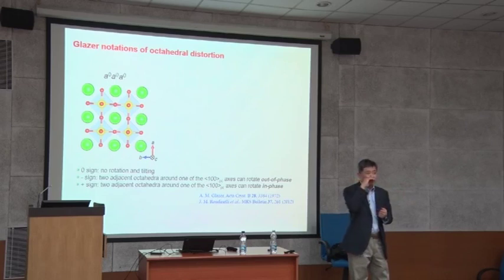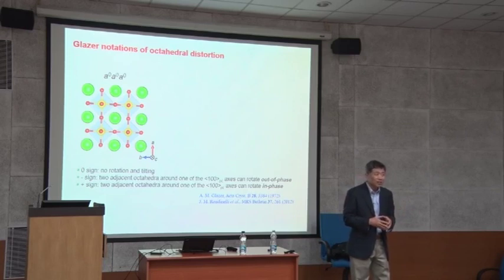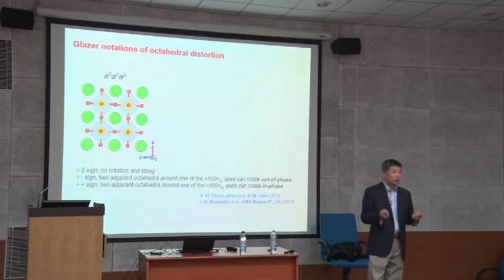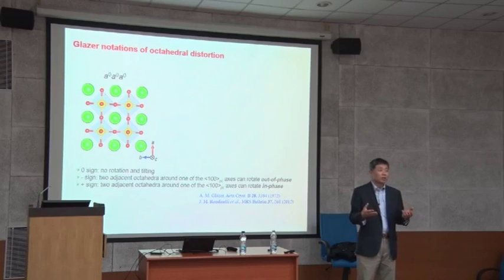So when they grow at high temperature, what is the problem? At 10 to the minus 6 and high temperature, what do you expect? STO should become conducting without oxygen. That's right. It forms a lot of oxygen vacancies. Strontium titanate creates a lot of oxygen vacancies when heated in vacuum. So after growth, strontium titanate is conducting. Then you cool down to room temperature and measure. You're not only measuring the 2D electron gas due to electronic reconstruction, you are also measuring conductivity coming from oxygen vacancies. That's why you measure very high conductivity, coming from bulk conduction.